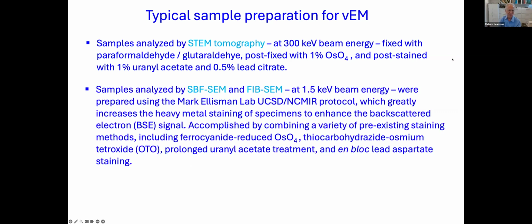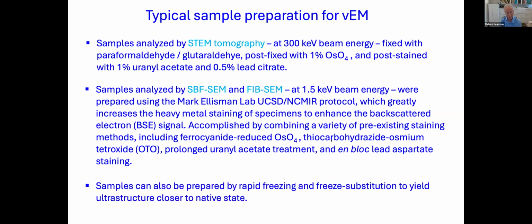And so for STEM tomography, you can use a somewhat light amount of stain, but special techniques were developed for the serial block face and the FIB-SEM because the signal really does depend on how many of those stain atoms you have. And so some variations were developed by Mark Ellisman's lab at UCSD, and that included the addition of some reagents and putting additional amounts of uranyl and lead into the specimen. Samples can also be prepared by rapid freezing and freeze substitution. We've made use of that for some of our work because we were concerned about the possible artifacts due to chemical fixation.